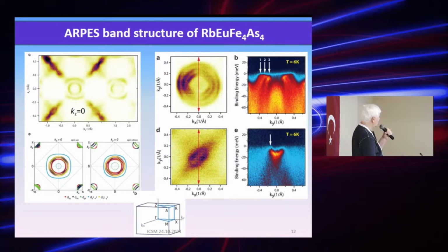And there are some figures, which at certain planes in the Brillouin zone can look like cylinders, but actually they sometimes look like a propeller. So some deformed cylinders. Anyhow, this picture is almost consistent with the theoretically calculated band structure, the DFT calculations. And there is nothing special, it's already well established. I don't see any puzzles here.